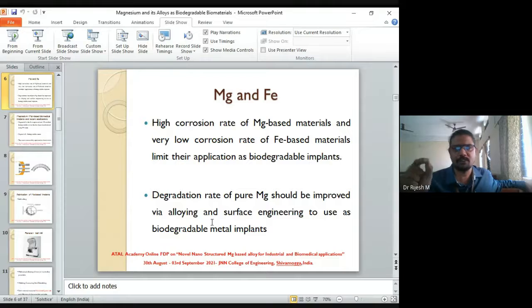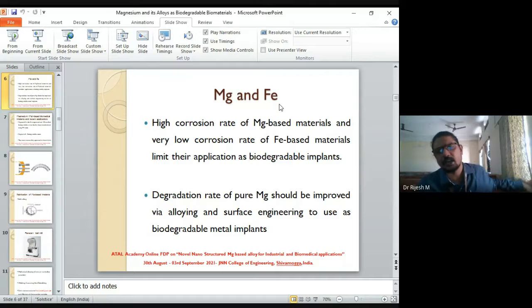It should not be more. If it's more, it becomes toxic. If it's less, again, it's a problem. So magnesium and iron, if they're working out fine, they're very good. But unfortunately, they're not good biodegradable implants, because of two problems. Magnesium has a very high corrosion rate. The amount of magnesium ions that gets liberated is very much. We don't need so much magnesium.